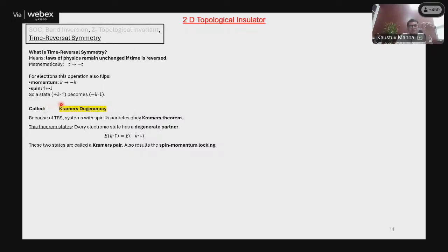And the consequence is called Kramers degeneracy. What Kramers' theorem says is that under time reversal symmetry, if you have a state k with up spin, then the degenerate partner is minus k with down spin. So this is the energy degenerate state, equal energy state. The consequence of this is that spin and momentum are locked. If a spin is moving in momentum space along the plus k direction and encounters a scattering cross section, then you cannot have the up spin go back in the opposite direction. That is not allowed, because the moment k becomes minus k because of the scattering, the spin also goes to the down spin. So spin and momentum are locked. This is the consequence of Kramers degeneracy.